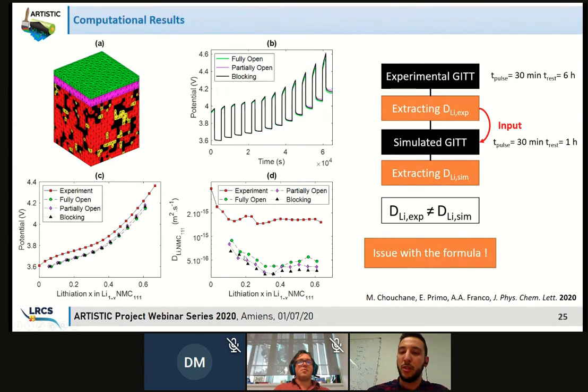But what's more is when you see it goes from blocking, partially open, to fully open, there are increasing values of diffusion coefficient, because this fully open case is the one closer to the hypothetical system where the equation was derived from.